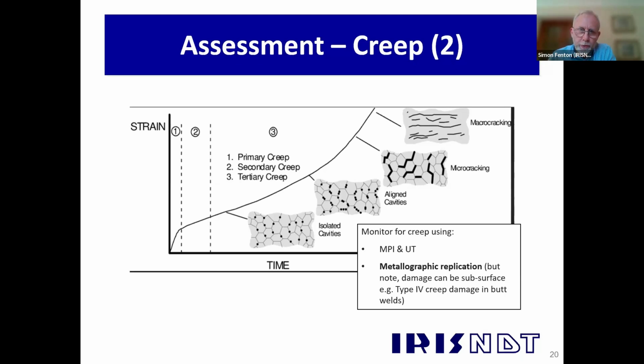But we always use a range of things in our toolbox, really, when we're looking for creep. So it's surface replicas, but MPI and UT are very important for us. So MPI, magnetic particle inspection, allows us to cover the whole component. And we would typically carry out the MPI before we do the replicas. And this is so that we can target the replicas on any defects that are shown up by the MPI.